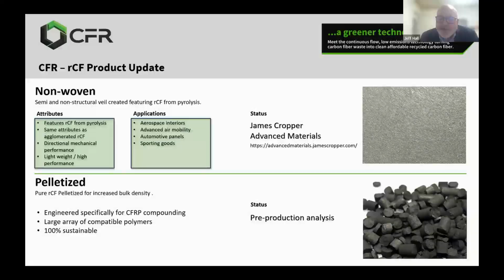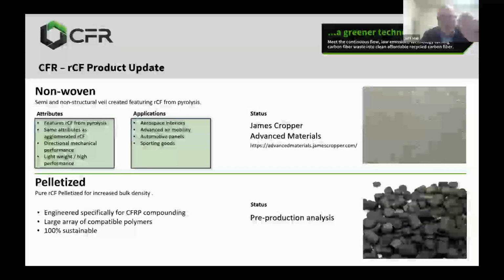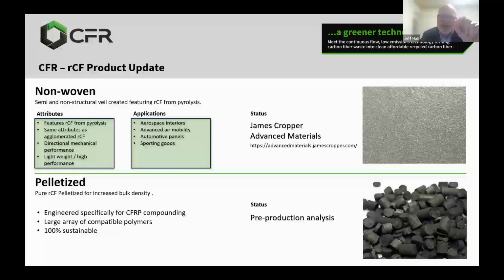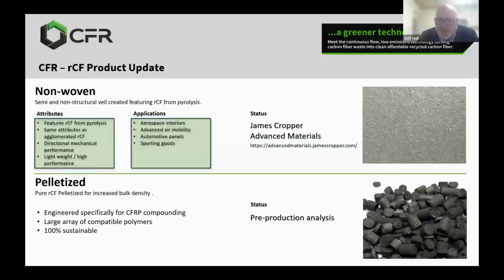Some other features of this material: there's various fiber lengths within this pellet that you're looking at, some as long as 8 millimeters that we've measured. And by having the various fiber lengths within the pellet, you're able to attribute certain properties that you would get from the various carbon fiber lengths to the compound that you're making or the polymer that you're working with. We also apply sizing to these pellets. In this image of the pellet, there's no binder material there. Outside of the sizing, there's no polymer holding that pellet together. It's essentially pure RCF with the addition of around 1.5% sizing, which makes this pellet compatible with a very large array of different types of polymers.